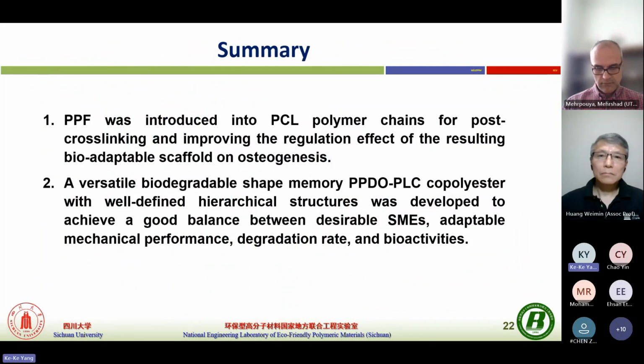At last, briefly to summarize: in the first example, we introduced the PPF segment into the PCL polymers, which not only can show the cross-linked site for the SMPs, but also show enhanced osteogenesis. In the second system, we can create well-defined hierarchical structures through microphase separation morphologies, which allows a good balance between desirable shape memory effects and adaptable mechanical performance, along with enhanced bioactivity.